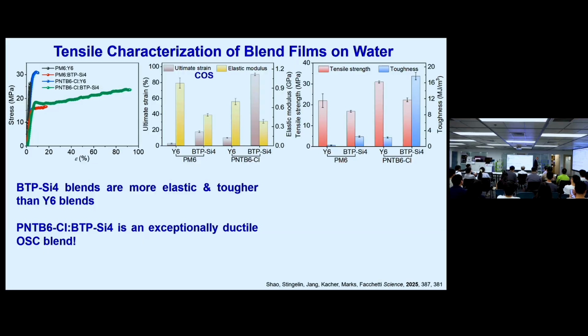But let's look at, say, now we're looking at blends. There's a donor and acceptor, and look at the green one here. How much you can stretch it. This is the stretching in percent before it breaks compared to all of these others. So this is the one with silicon. And let's look at the crack onset. So you want this to be as low as possible. And so here's Y6, but all of the silicon ones are much better. This one, that one, and that one. And the tensile strength and toughness, again, Y6 is not very good, but the ones with the silicon are much higher. So what it's saying is that the blends, when the silicon constituents are there, are much more elastic and tougher than with Y6, the one that everybody knows and loves, and it's an exceptionally ductile material.